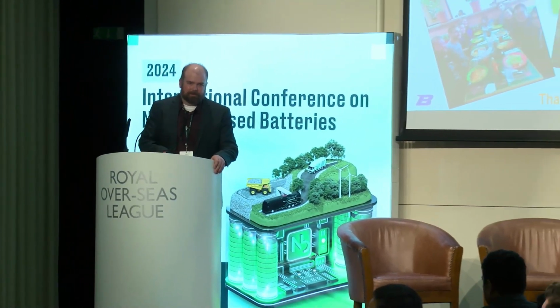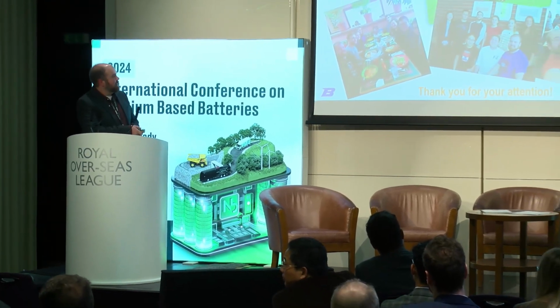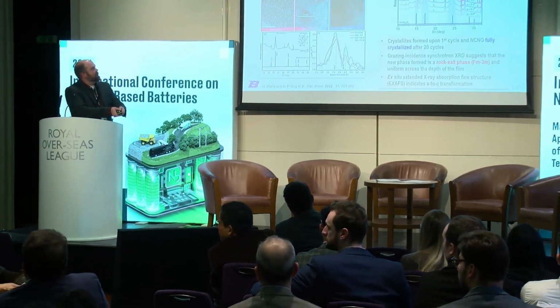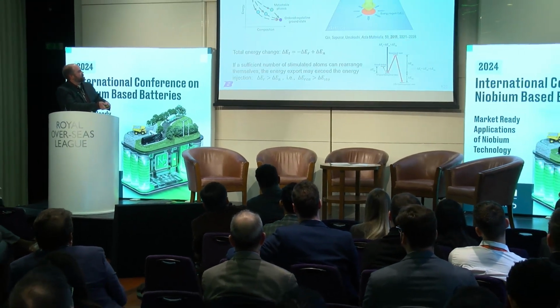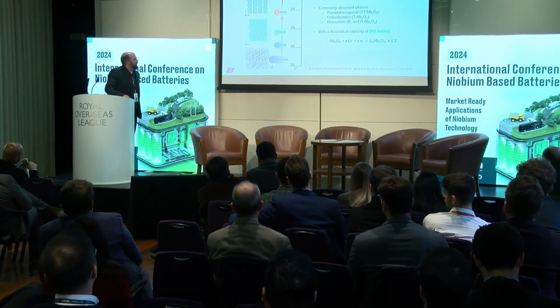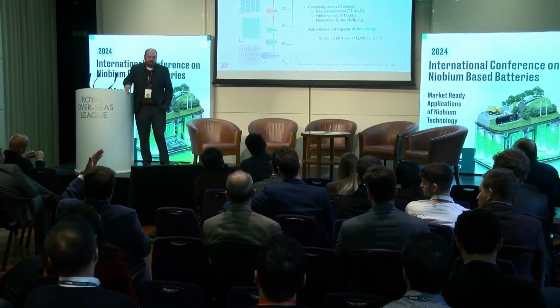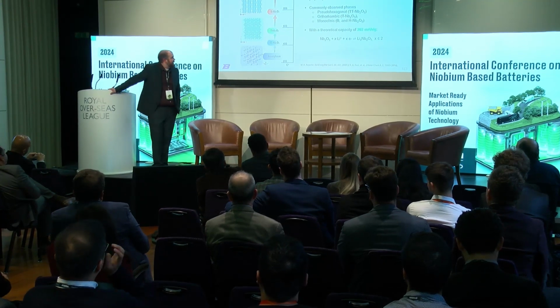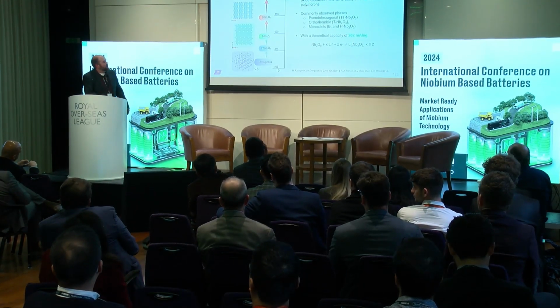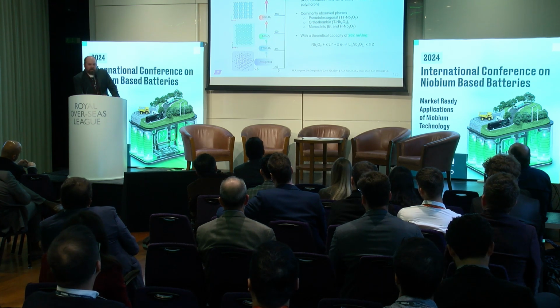Ron, you were fast. My question is regarding the rock salt structure, if we can have it only electrochemically induced, because at the lab in our factory in Brazil, we never saw rock salt structure when you start from the amorphous phase, increasing the temperature. So I would go back and look at this chart here. That's the typical phase transformation that you see in the lab. So what I would say to that is yes. Right now, that's the only evidence that we have for forming the rock salt, through electrochemistry.